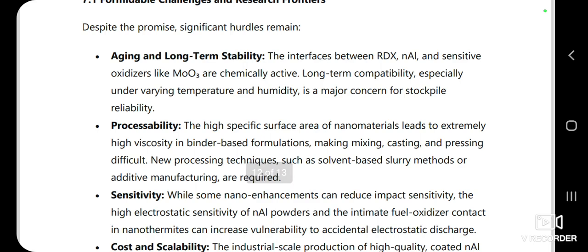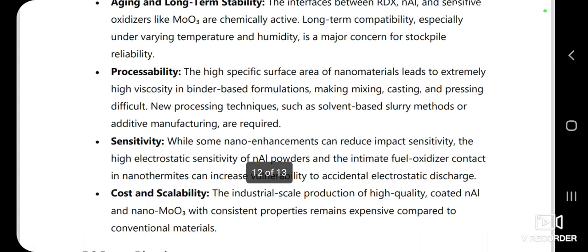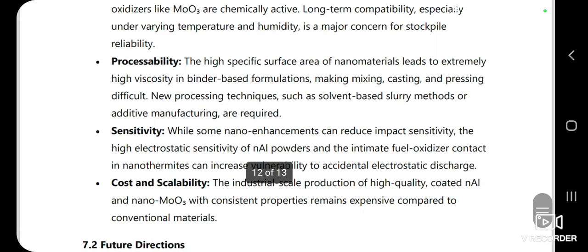The other is processability. The high specific area of nanoparticles leads to extremely high viscosity in binder based formulations, making mixing, casting, and pressing difficult. But new processing techniques such as solvent based slurry methods or additive manufacturing are required. The next is about sensitivity. While some nano enhancements can reduce impact sensitivity, the high electrostatic sensitivity of nano aluminum powders and the intimate fuel oxidizer contact in nanothermites can increase vulnerability to accidental electrostatic discharge.